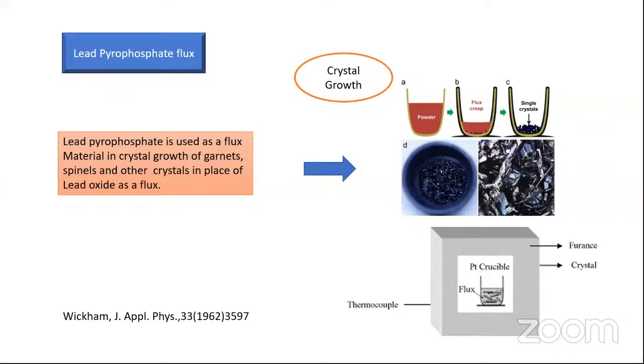But there are many materials which do not dissolve in water, even in alcohol and other solvents. For them, different pyrophosphates and different oxides work as a solvent. So what people do, they take a platinum crucible and heat different types of oxides and pyrophosphates, and make a high temperature solution. There they dissolve the material which they want to grow into crystal form. After dissolving it, after cooling the crucible to a desired temperature, the same process takes place as in the case of sodium chloride growth in water. Same process, but here we are using high temperature molten salts, and the crystals are grown. So molten salts are known as a flux.